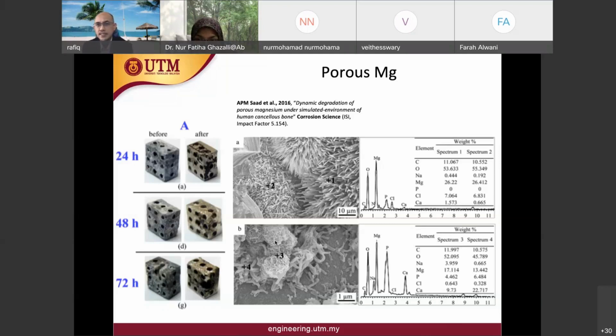It's degraded. So again, if we can somehow design a porous magnesium that once it is dissolved, the bone also heals completely, that would be interesting. At the end of the day, we want the bone to heal. We need stability in order for bone to heal. But if we can somehow develop an implant that provides the stability initially whilst the bone heals, and then once the bone completely heals, the implant also dissolves completely. Wow, that would be interesting, isn't it? So this is our research work on porous magnesium.